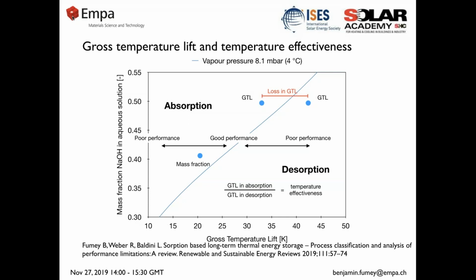We have on the x-axis the gross temperature lift, which means the temperature difference between the desorber and the condenser in the charging process, and the evaporator and the absorber in the discharging process. On the y-axis, we have the mass fraction or concentration of, in our case, sodium hydroxide. And the blue line is the vapor pressure line in our case at an evaporating temperature of 4 degrees, and absorption is always going to be above the line and desorption is going to be below the line.